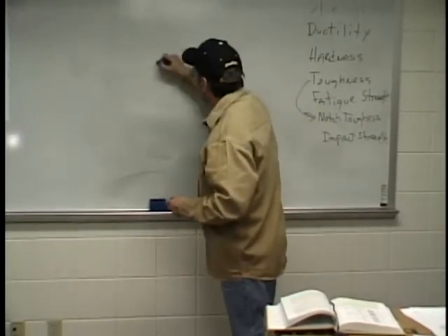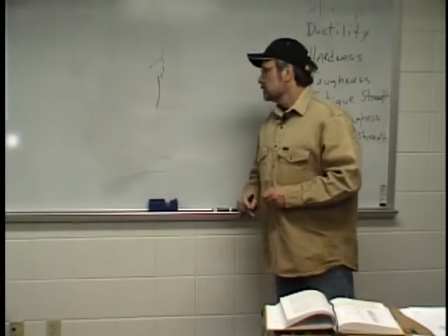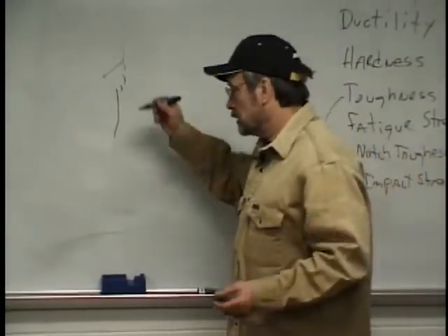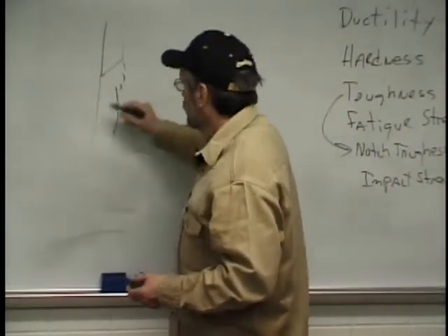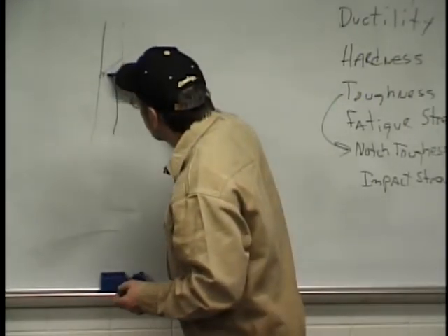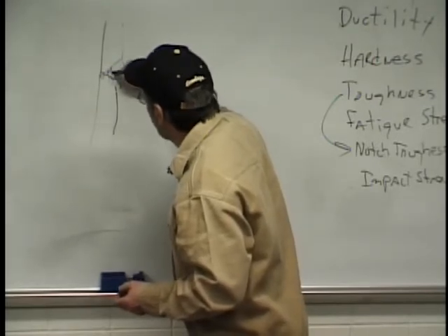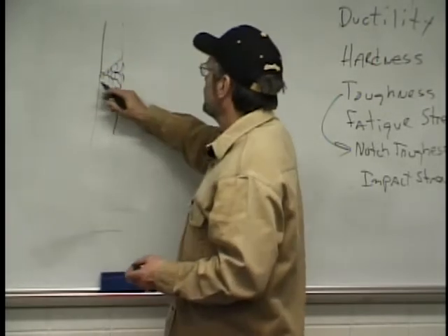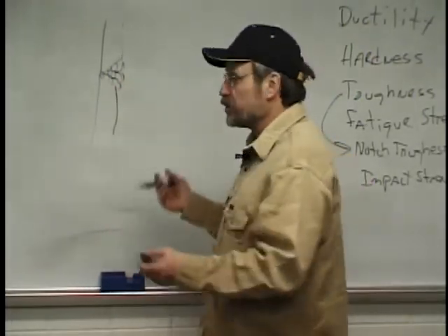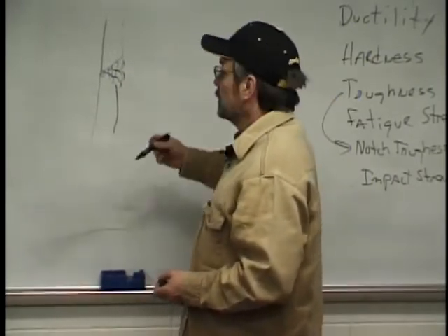People have asked me a number of times, well, Uncle Bob said that I had to make this weld, and it had to be capped in three passes. The welding procedure doesn't say so, Uncle Bob says so. Well, Uncle Bob, you didn't write the procedure. The only reason you would have to do a weld in a particular sequence is for tempering purposes, so that it will stress relieve the previous weld. And they call them tempering beads. There are actually procedures for doing that. Otherwise, it takes as many welds as it takes to fill it.